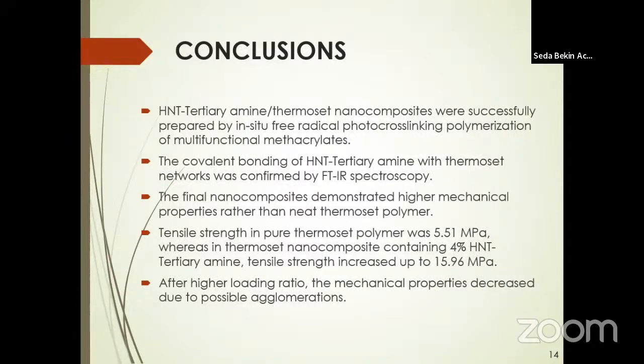At the end of the study, we can reach the following conclusions. Halloysite tertiary amine thermoset nanocomposites were successfully prepared by in situ free radical photocrosslinking polymerization of multifunctional methacrylates. The covalent bonding of halloysite tertiary amine with thermoset networks was confirmed by FTIR spectroscopy. The final nanocomposites demonstrated higher mechanical properties than neat thermoset polymer. Tensile strength in pure thermoset polymer was 5.51 megapascals, whereas in thermoset nanocomposites containing 4% halloysite tertiary amine, tensile strength increased up to 15.96 megapascals.